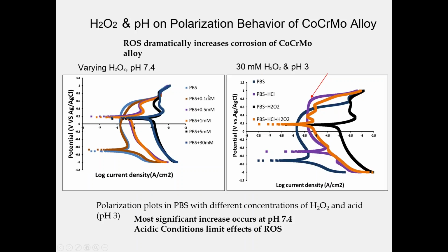we see that with increasing concentrations of hydrogen peroxide from 0 to 30 millimolar, we get a very profound shift in the corrosion behavior of cobalt chromium, where the corrosion currents rise about 40 times just by the presence of these reactive oxygen species up to about 30 millimolars. Indeed, at 5 millimolar, we're seeing as much of an effect as at 30 millimolar.